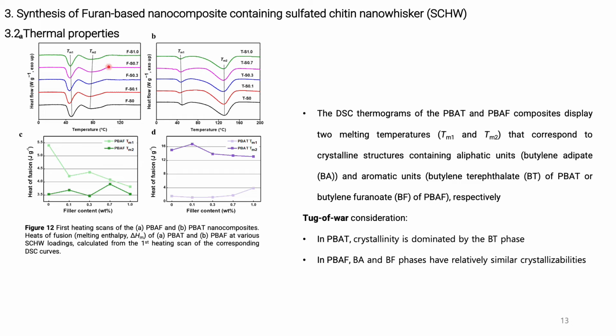As we can see here, when incorporating the nanofiller, the melting peaks of the aliphatic BA segment in both the PBF and PBAT composites, and those of the aromatic BF in the PBF composite, shifted to lower temperatures when the filler is included. They also generally exhibit a lower heat of fusion. In particular, the BA segment in PBF shows a noticeably lower heat of fusion at 0.1 weight% than the BF segment in PBF or the BA segment in PBAT, whereas the BT segment in the PBAT composite appears to be almost independent of the nanofiller loading.